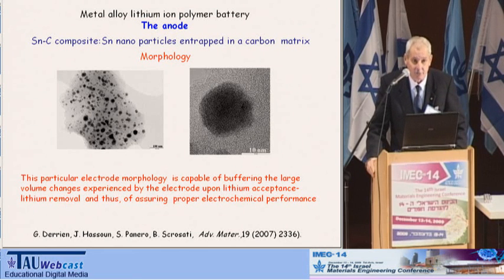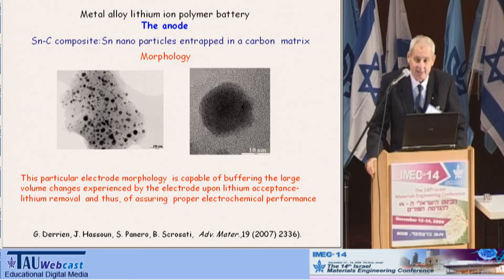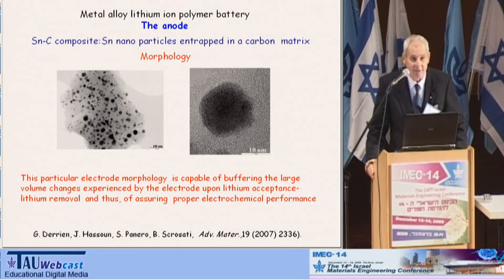However, it is also important for electrode material not only to have a nanostructure which improves rates and kinetics, but also to have a high tap density, because otherwise we end up having a very low volumetric energy. And also, if you use nanoparticles as such, their stability is very poor. They react very easily. So in this way, we maintain at the micro level low dimension particles, a nanostructure, but at macro level we have a dense structure.